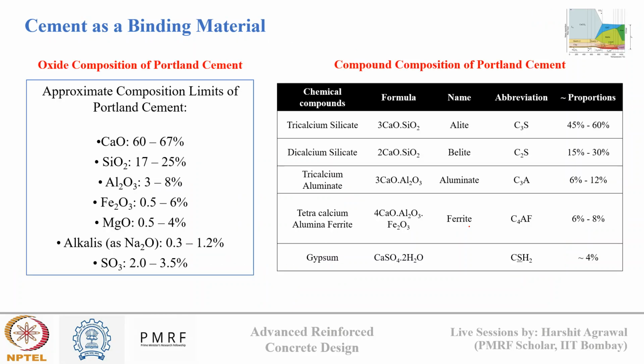Now, after passing through the kiln phase, the limestone and clay, the raw materials that we are using, upon exposure to high temperature, form different oxides of calcium, silica, and alumina after liberating CO2 and moisture. For a Portland cement, the composition of oxides is of the order shown in this box. CaO is around 60 to 67%, SiO2 is around 17 to 25%, alumina oxide is around 3 to 8%, iron oxide is 0.5 to 6%, magnesium oxide 0.5 to 4%, alkalis are present in small amount 0.3 to 1.2%, and there is some amount of SO3 also, 2 to 3.5%. So this is the standard oxide composition that we get in Portland cement.